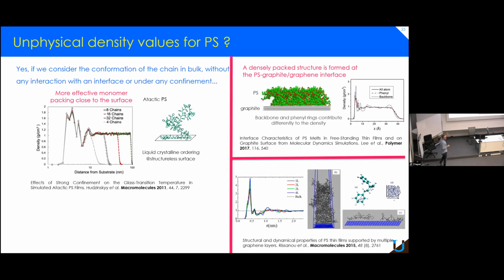Some of what I'm worried about has to do with the definition of the width of the film. You never actually measure local density within the layer. You measure a cumulative effect; you integrate an effect over the full layer. So it's somehow related to total material adsorbed on the material divided by the volume, which is the surface times H. So your definition of H must somehow enter here.